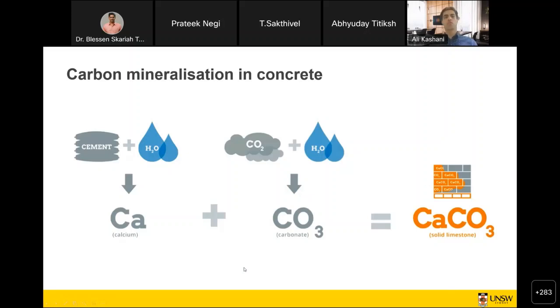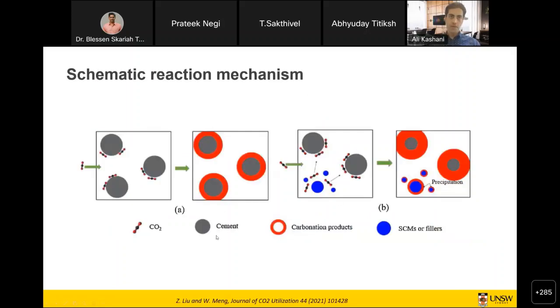So essentially, you have some calcium compounds in your cement mix that get reacted by the CO2 that you introduce during the curing or during the mixing, and then you get calcium carbonate. That calcium can come from cement or any other materials containing calcium. In this case, you can see the cement and CO2 developing the carbonation product on cement grains.